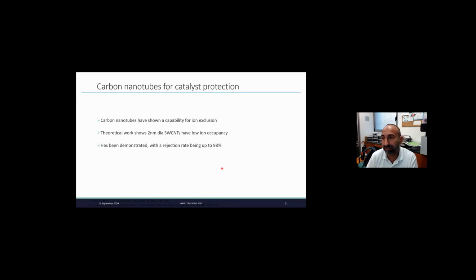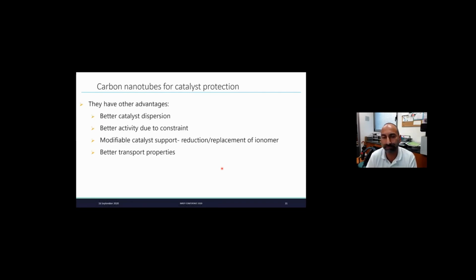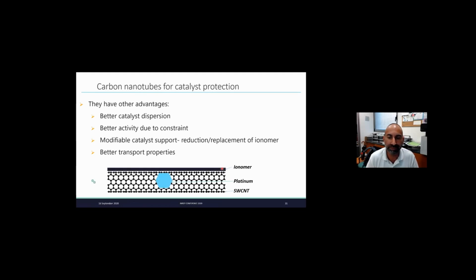And it has been demonstrated that you can get a rejection rate of about 98% by using this type of nanotubes for filtration. So it's very good for the dispersion of the catalyst, for the activity of the catalyst, and then you can modify your carbon nanotubes because that's really well known. You get a very nice toolbox for nanotubes today. So the idea is to put the platinum inside, and that we're gonna get some hydrogen diffusion, dissociation, and proton going out from the side.